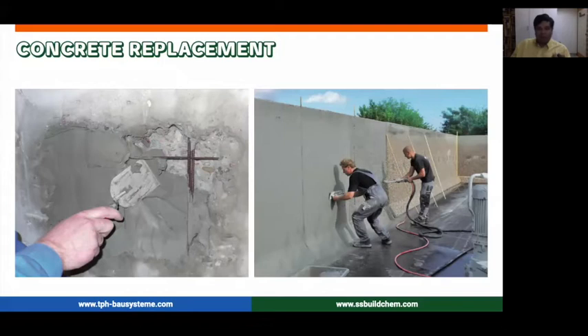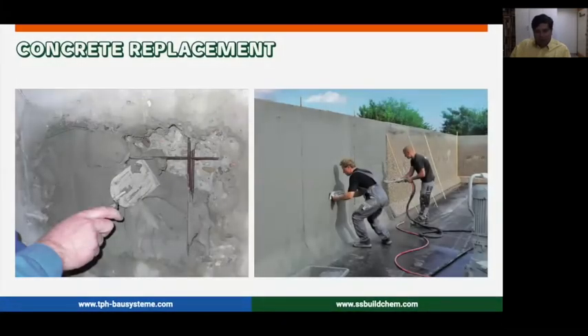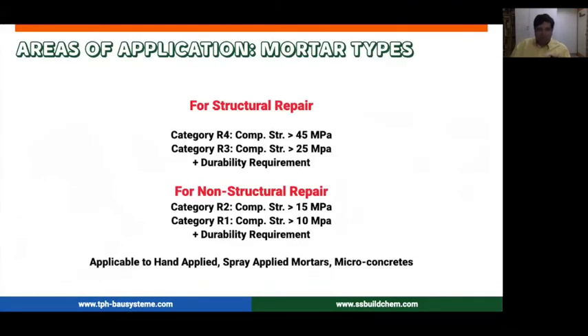Then comes your concrete replacement system. These are what we call polymer modified mortars. We recommend that you use a ready-to-use mortar, because getting sand, getting cement, and then using a polymer, mixing it on site, becomes too much of a hassle to get all these different things together on site. So it is recommended to use pre-bagged polymer mortars. You can get it both as a trowel applied grade and as a spray applied grade. It's very easy. You just have a mortar spraying machine, and you can do large areas in one go.